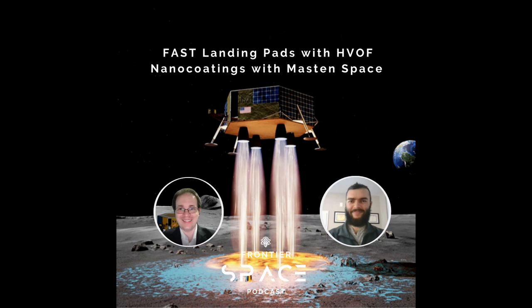The end result of that was we tested some coupons of the alumina ceramic we're looking at using, and they performed quite well. They stood up to the expected lunar conditions and beyond. And even though these weren't manufactured with the FAST process, they give us a good peek at, yeah, this is a suitable material for this use case. And it gives us margin. So that's always a nice place to be from a technical perspective.